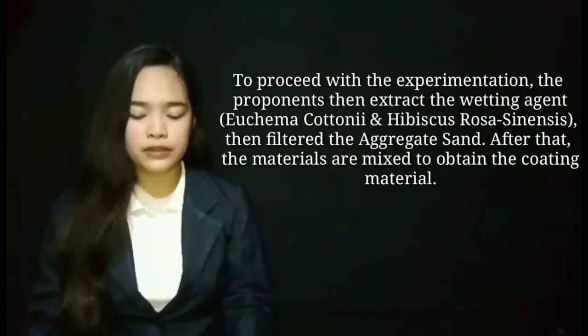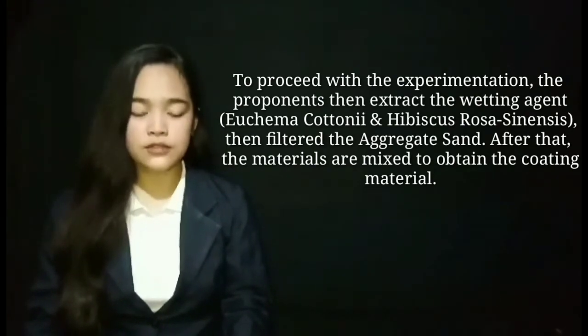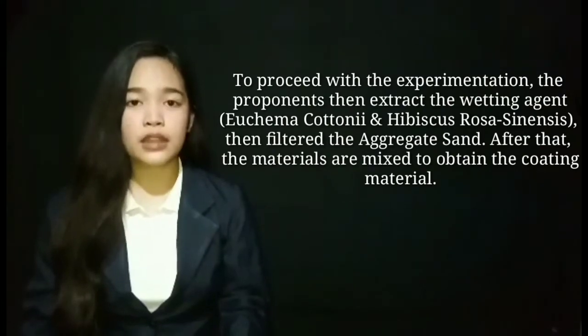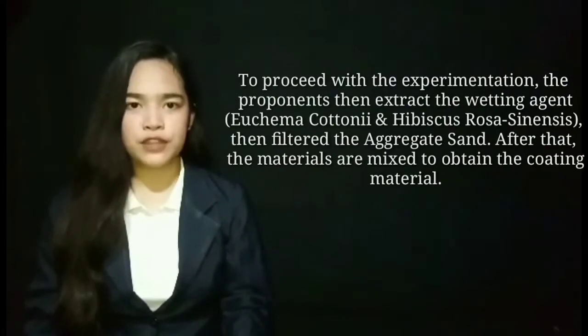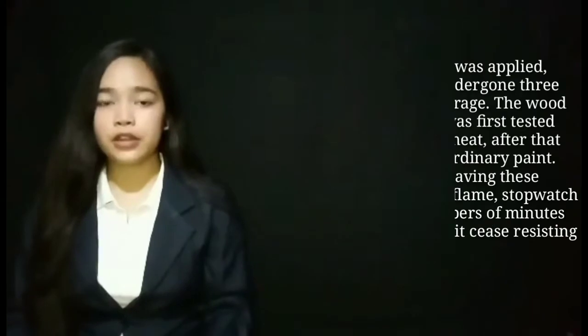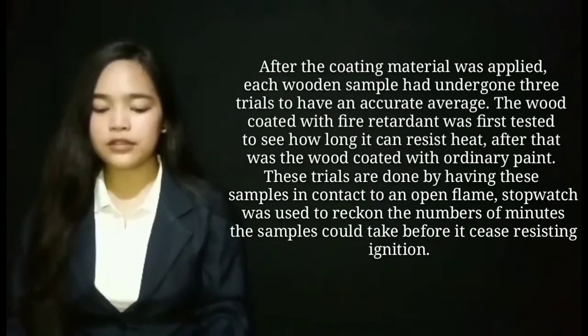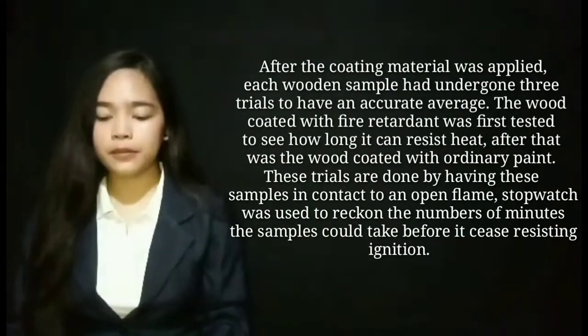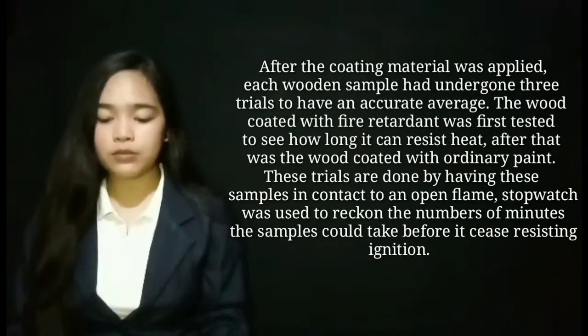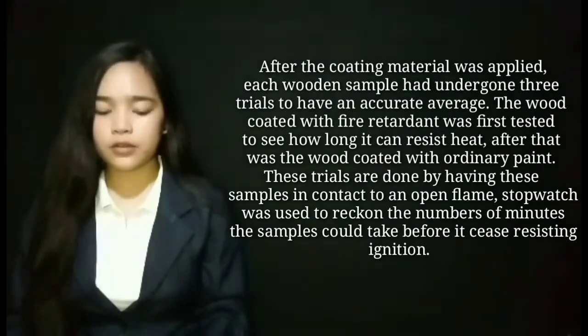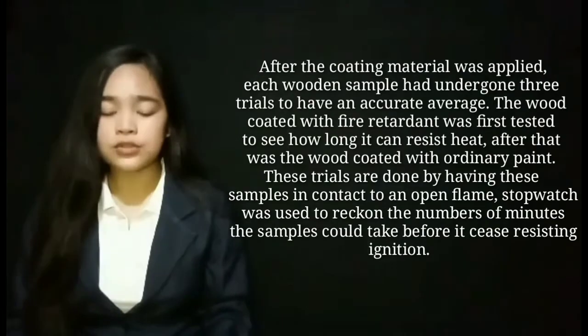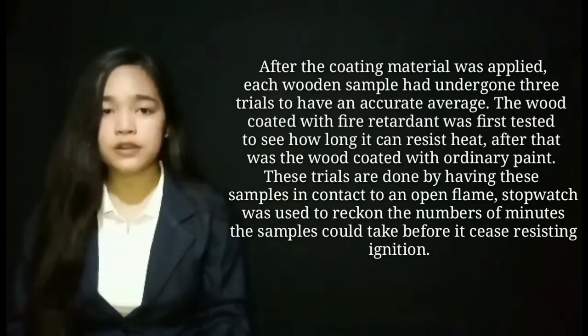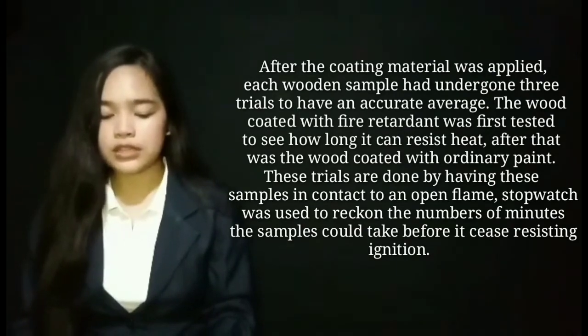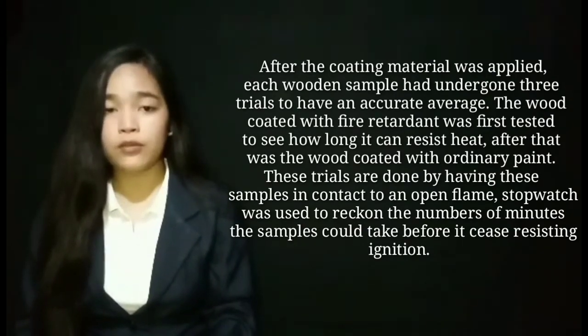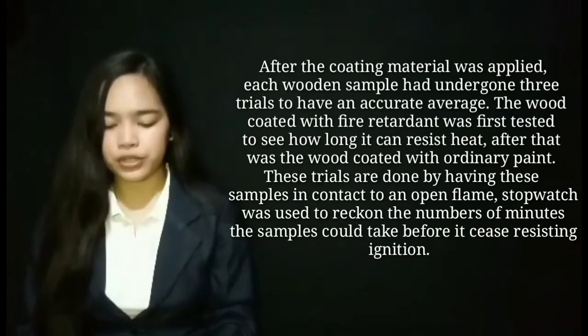The prepared raw materials were then mixed in the container and once again strained for smoothing. The finished product was then varnished onto 3 different wooden samples. The proponents also coated another 3 wooden samples with an ordinary coating, for it will be used for comparison. All the samples then underwent experimentation, which is its application to an open flame with an average heat temperature.